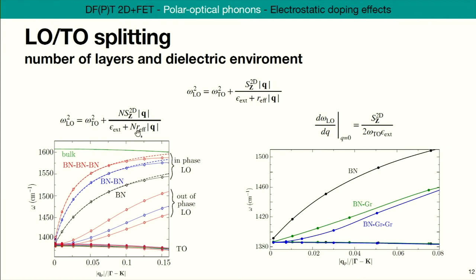And then it also comes in the screening part here. That means that the curve gets closer to the 3D bulk dispersion faster and faster at smaller and smaller momentum. So it describes exactly what we see here, that the curve goes and sticks to the dispersion that we see up there. And here, in-phase just means that we're looking at the mode where the dipoles are in phase in different layers, such that the fields add up. The out-of-phase mode is where the dipoles are out of phase, and the fields cancel each other. And this is why you have, in the end, zero slope here.